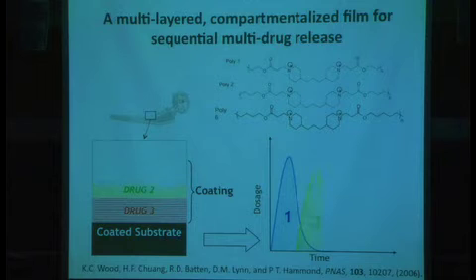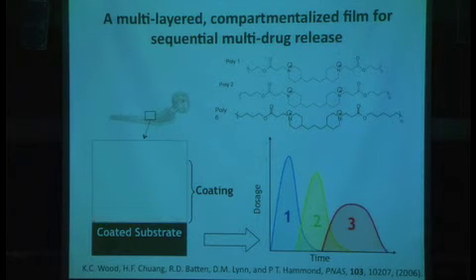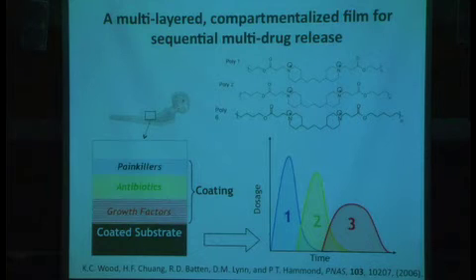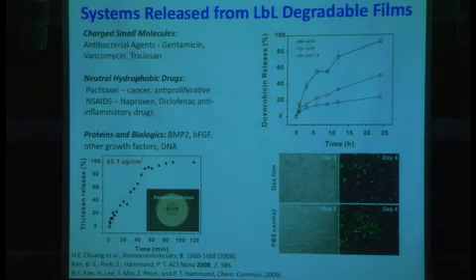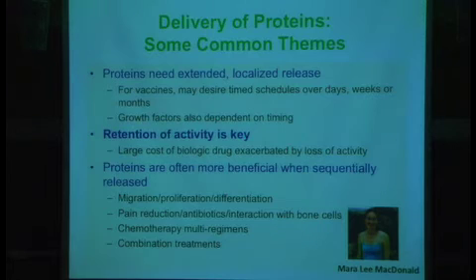There's another advantage to using layer by layer, however, and that's the fact that one of our components in many of these systems actually is the drug, meaning it's one of the charged species that we incorporate into the film. And in that case, we actually end up with very high drug loadings of these materials. So we've incorporated a broad range of different kinds of materials. We've looked at gentamicin, vancomycin, and a range of other antibiotics. I'm just going to describe what we're doing with the biologics very briefly.